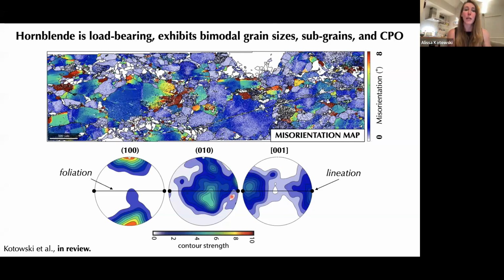What we can see from this misorientation map is that the patterns of intracrystalline plasticity are extremely systematic. So we see some dislocation walls or subgrain walls that are aligning parallel to the foliation, some perpendicular to the foliation. A lot of these big grains have both, and a lot of these big grains have an increased amount of misorientation near their margins. So the fact that we see these really systematic orientations of subgrain walls tells us that there are dislocations moving through these grains, and they're doing that in a very systematic way. They're moving along specific slip systems on certain planes in certain directions.